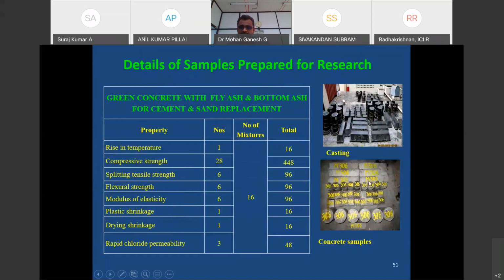So in the beginning itself, I said to you, for any alternate material, we have to do vigorous testing. In that case, for this mix, we have done various tests like rise in temperature, compressive strength, split tensile strength, flexural strength, modulus of elasticity, drying shrinkage, and RCPT with various numbers. And this is, per mix, how many specimens we cast at our lab. This is the total number of specimens.